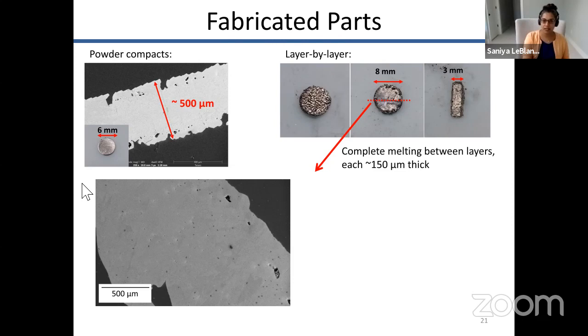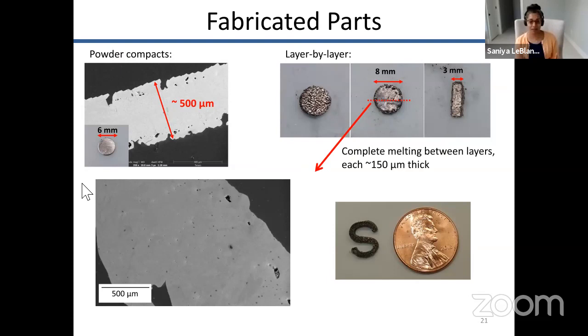What's really interesting about this, though, is that with traditional thermoelectric manufacturing, you can't make unique geometries. You're just stuck with something that is this disc shape or this bar shape. But because we're using the additive manufacturing technique, we can make a unique geometry. With the traditional thermoelectric manufacturing techniques, it's very hard to make this kind of curvy S-shaped structure that you see in the bottom right. But with the laser additive manufacturing technique, it's fairly simple to do that. So we're really excited that we're able to show this on thermoelectric materials.